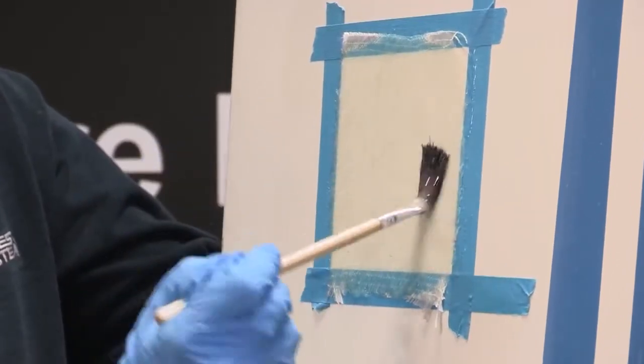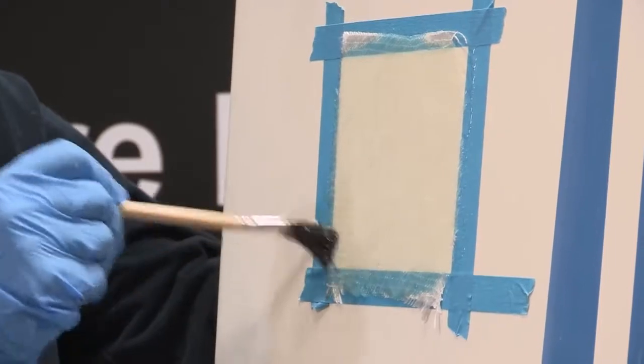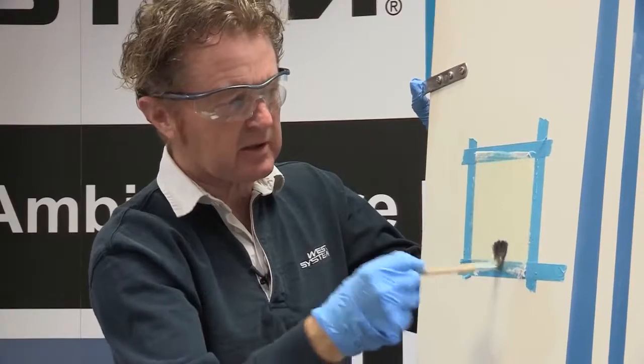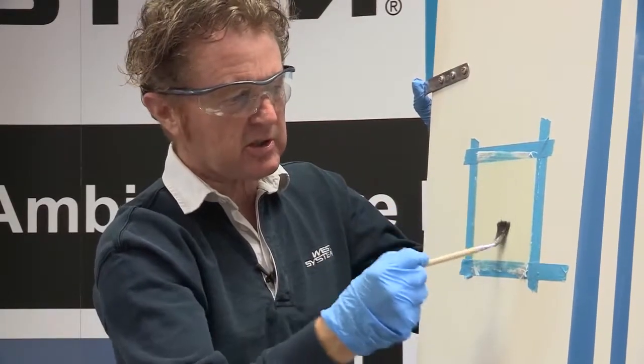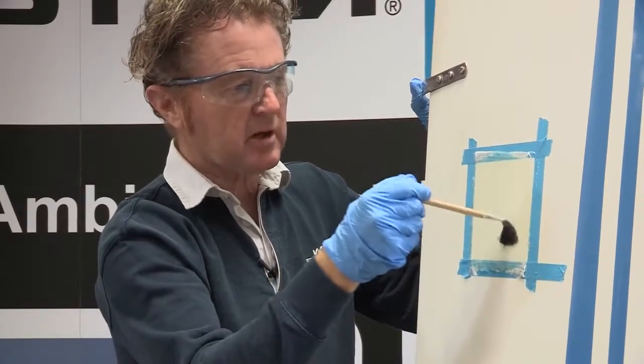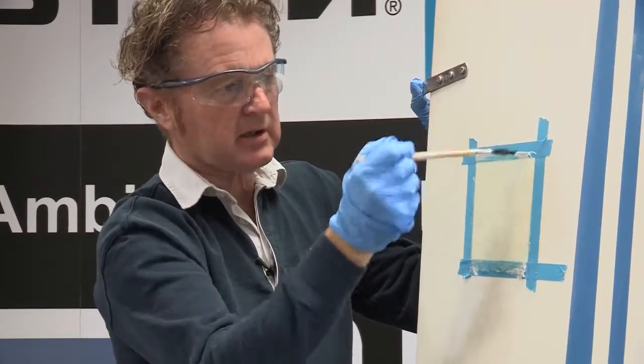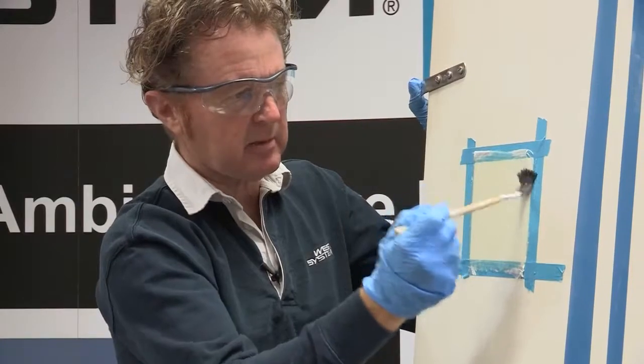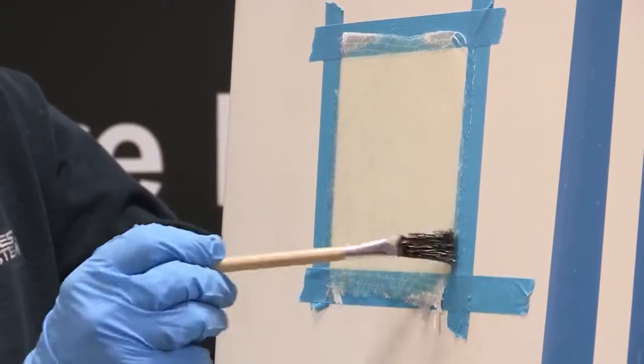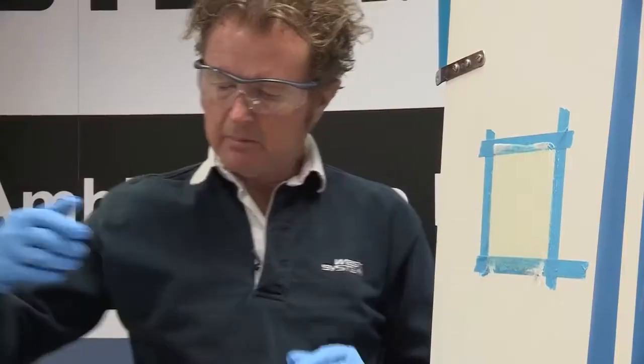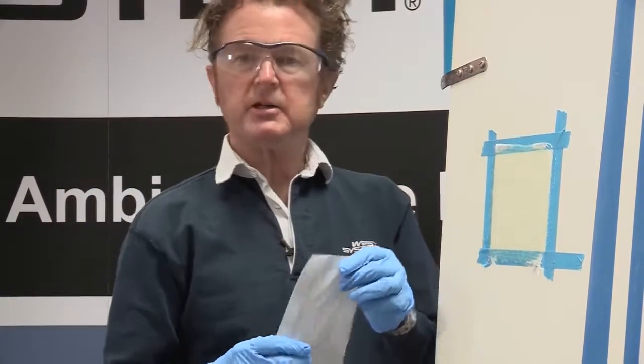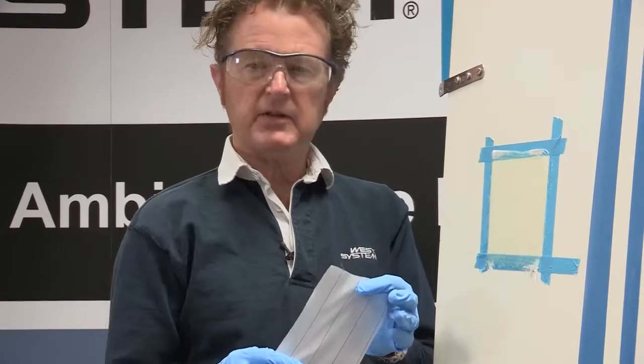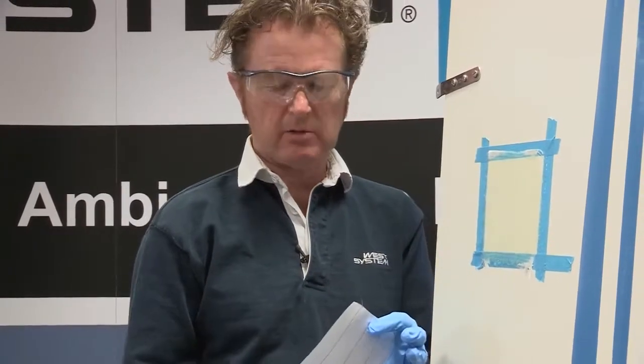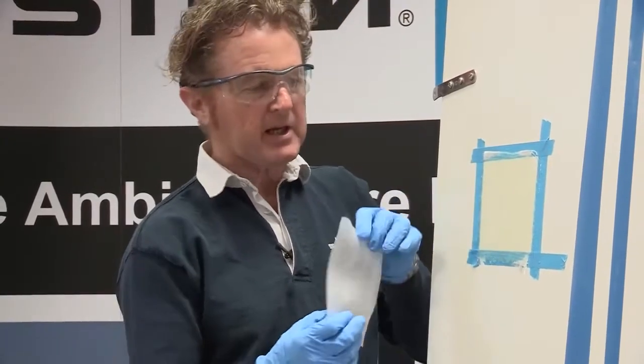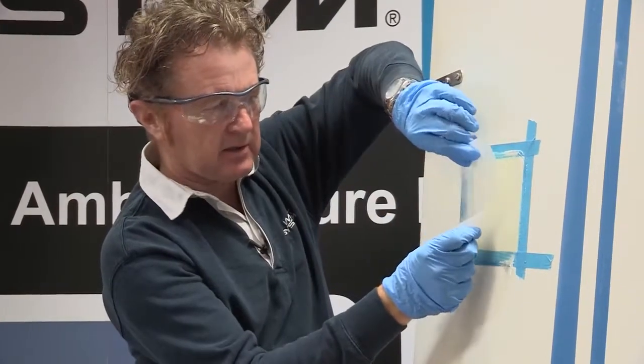It's best practice when you're using epoxy with glass to go through this process of either using a brush to stipple the surface down or using a foam roller to consolidate the glass and break down any air bubbles. It looks well consolidated, but I'm also going to put something on the surface of this, a product that we call peel ply. This is an essential when working with epoxy because by placing it over wet epoxy and